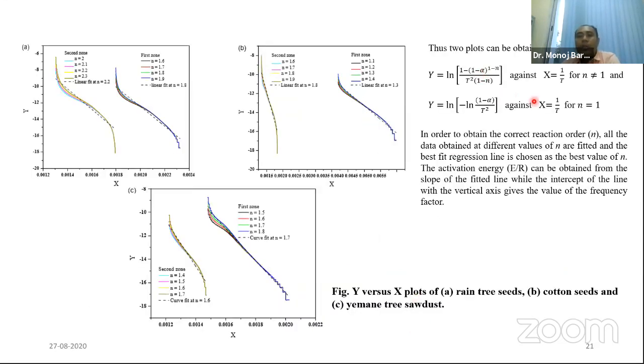Using these y and x values, if we make plots for the two zones, the first zone and the second zone, for different values of reaction order, we get different types of plots. And finally, we use the best regression fit line. This best regression fit line, for example, is found for the reaction order, say in this case for the first zone, n equal to 1.8, and we can show it by the dotted line. And normally we get this kind of straight line for both the first zone and the second zone.